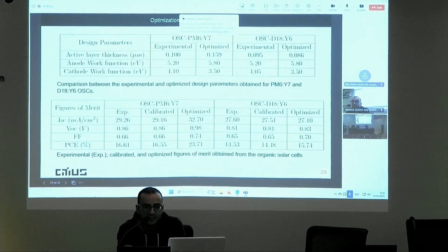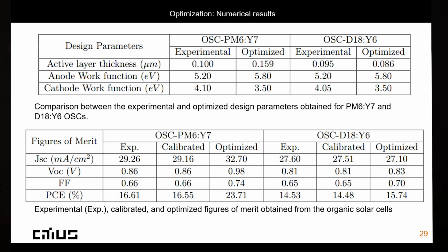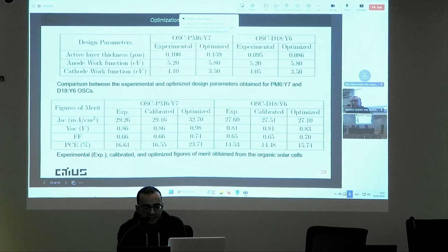Here in these tables, I present the numerical results. The first table shows a comparison between the experimental and optimized design parameters for the active layer thickness and the work functions of the anode and the cathode. As you can see, the anode work function was increased to 5.8 electron volts, and the cathode work function was reduced to 3.5 electron volts. This could improve the open circuit voltage and the fill factor, as you can see in the second table, for each organic solar cell. Also, the active layer thickness was modified for each organic solar cell. In the first case, this thickness was increased from 0.1 microns to 0.159 microns.